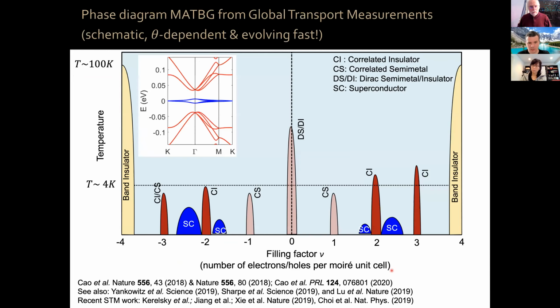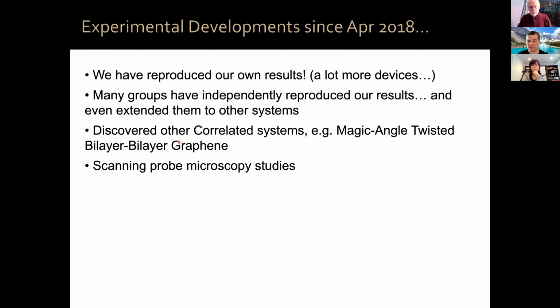Now, we have discovered since then several other correlated systems based on this Moiré physics and twisted physics. For example, twisted double bilayer graphene. This is a system where you have regular bilayer graphene, two layers of graphene with zero-degree angle between them, another bilayer graphene, and now you twist them pairwise, two twisted with two. So you form this twisted double bilayer graphene. It's an interesting correlated system with interesting magnetic properties. It is not superconducting though.